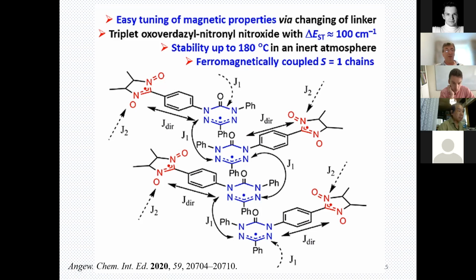They survive at temperatures of more than 180 degrees Celsius. They can also be sublimed at very low pressure, so they can actually be transferred via vapor to any surface. And what is also important for this series of radicals, for the first time we found a ferromagnetic triplet diradical, which is ferromagnetically coupled in spin 1 chains.